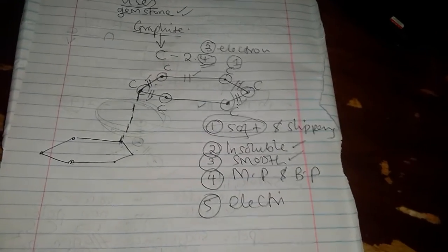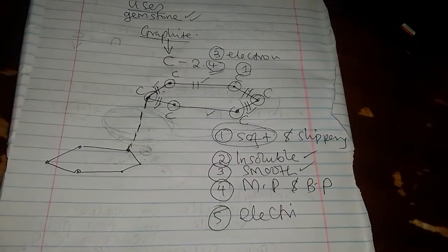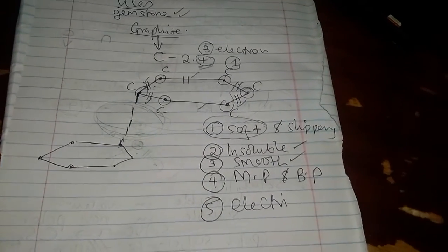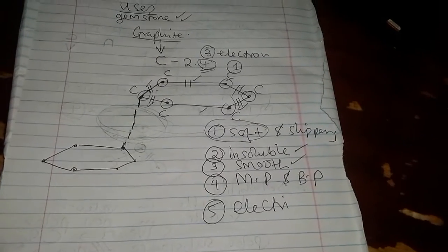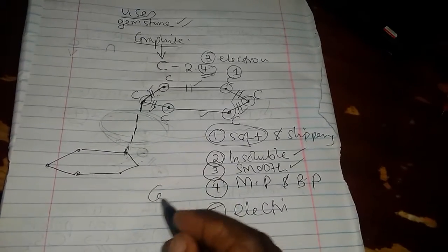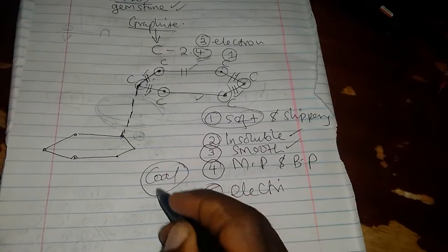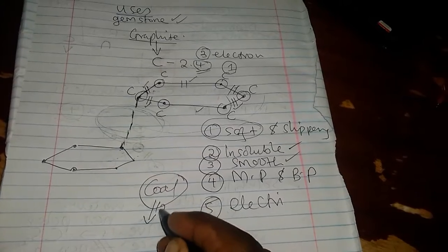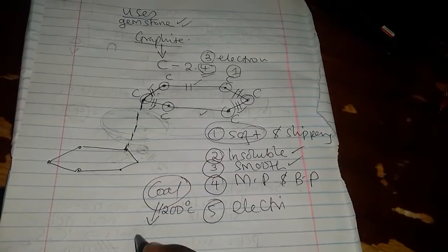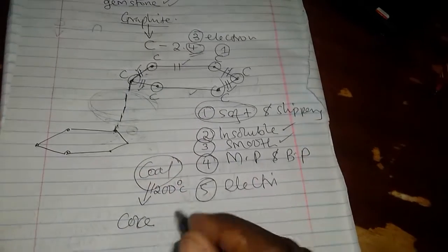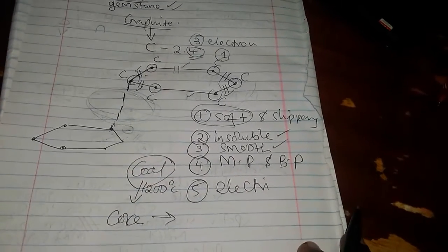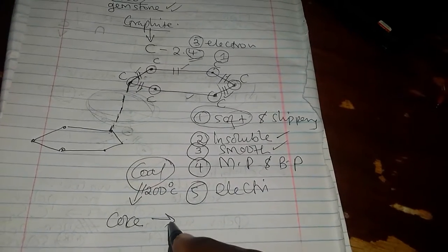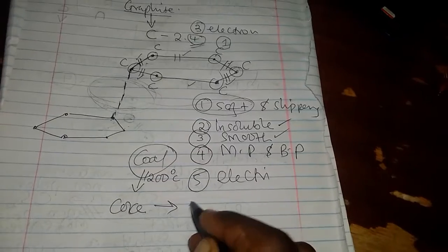Now, scientists have been saying that graphite is less abundant in the environment. So what happens for us to have more of the graphite? You'll find that coke gets obtained from coal. So if this is the coal that is a mineral, it gets mined. They heat this coal in an inadequate supply of air to around 1200 degrees Celsius. They obtain coke. The coke also undergoes heating. It gets subjected to very high temperatures and pressure to obtain graphite.